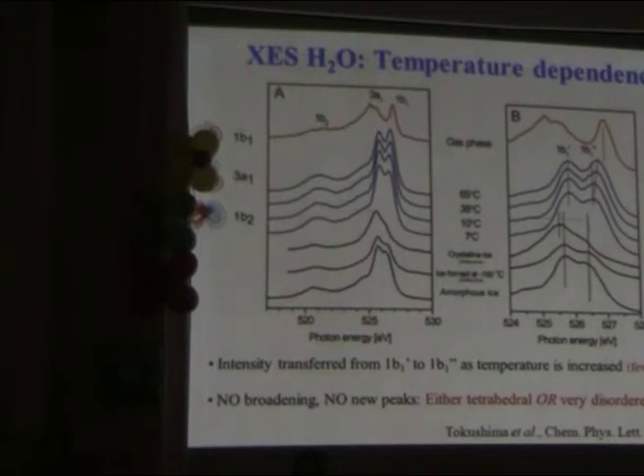Here's X-ray emission spectroscopy now. On the left we have the full spectra. Here we have gas phase. Here we have crystalline ice, and we can see there's a shift between gas phase and the condensed phase. Now, in the liquid, we get a split with one peak close to the gas phase and the other peak close to the position in tetrahedral ice. We have a sequence of different temperatures, and we can see that when we heat the liquid, the peak here, which is close to the tetrahedral position, goes down in intensity, and instead the other one grows in intensity.